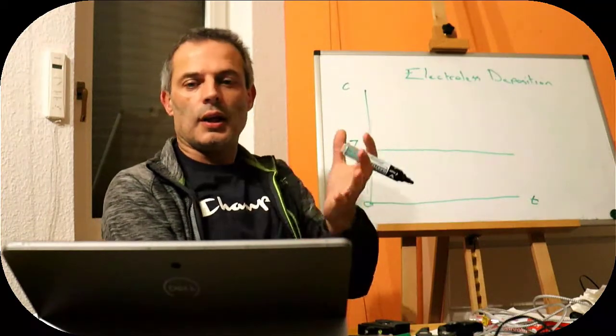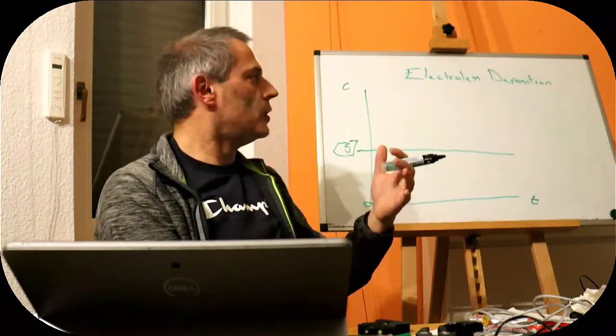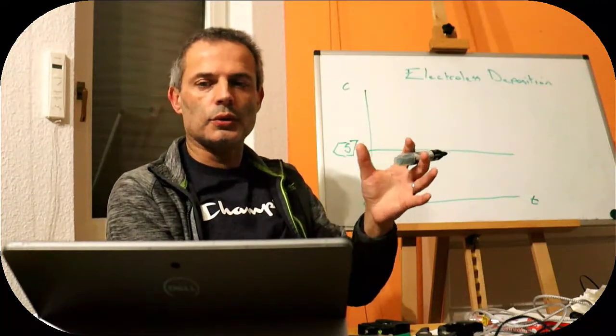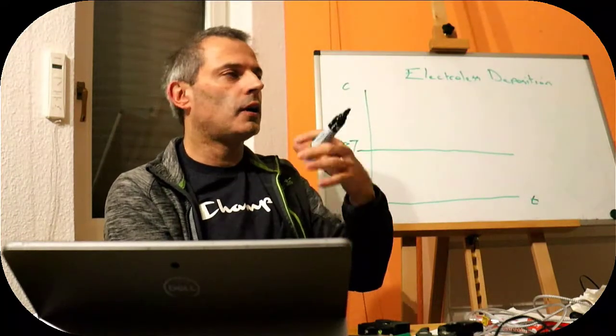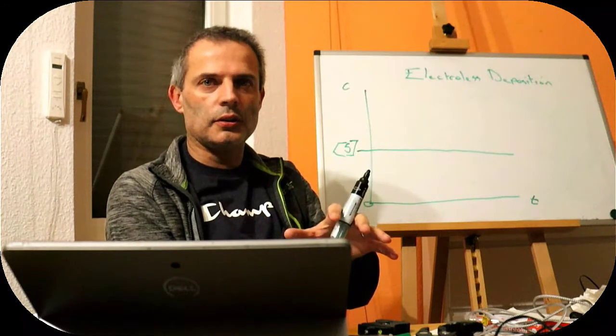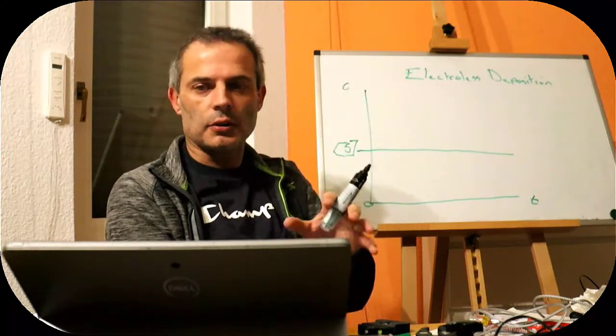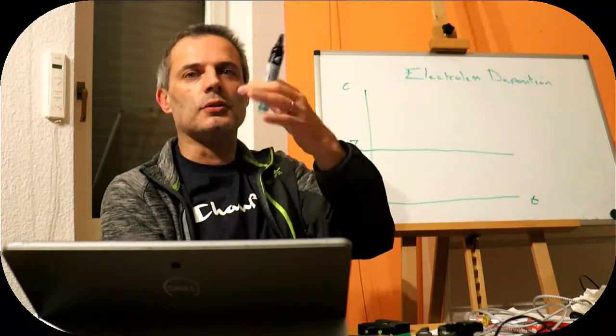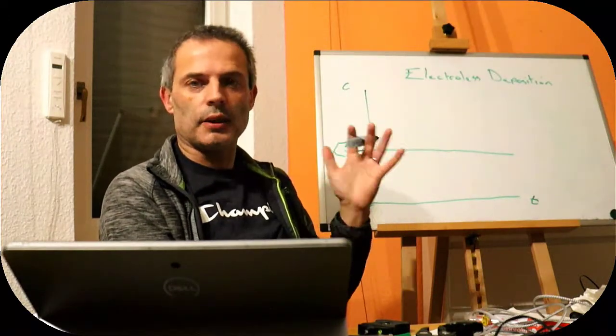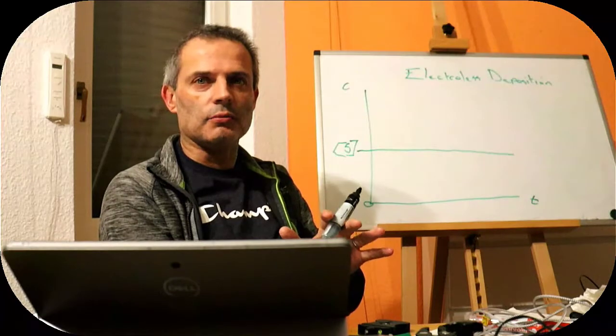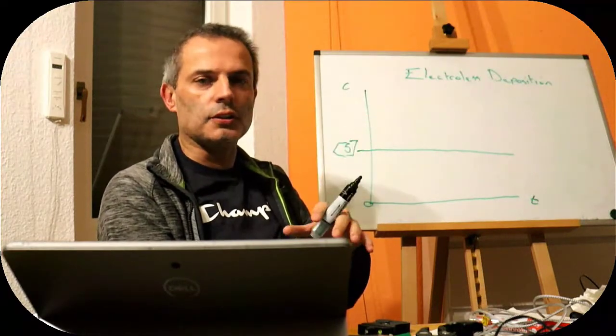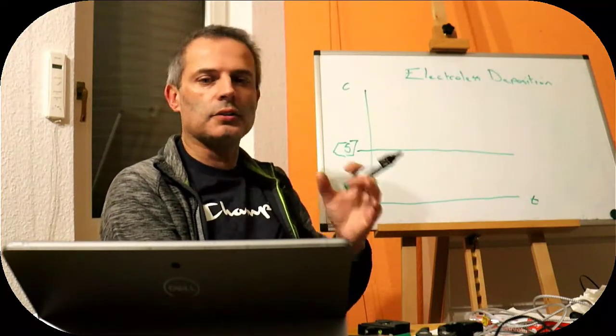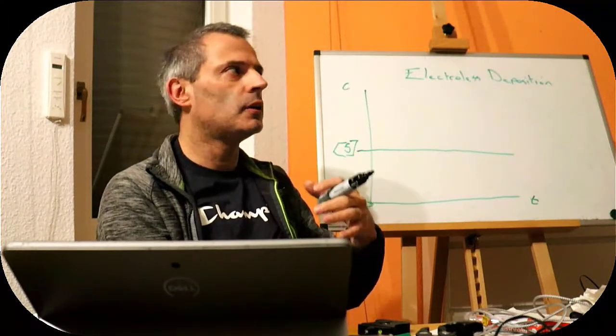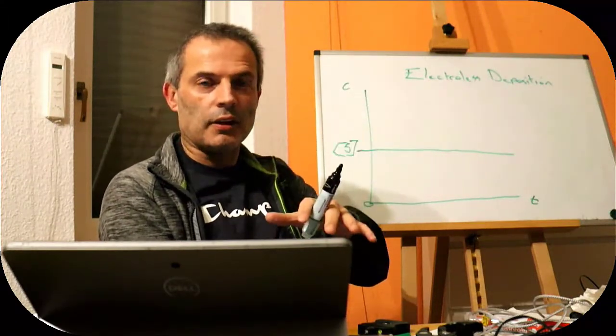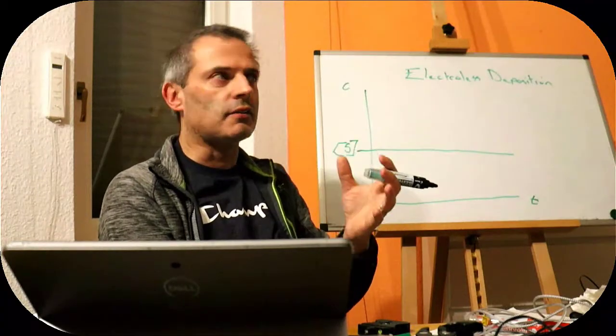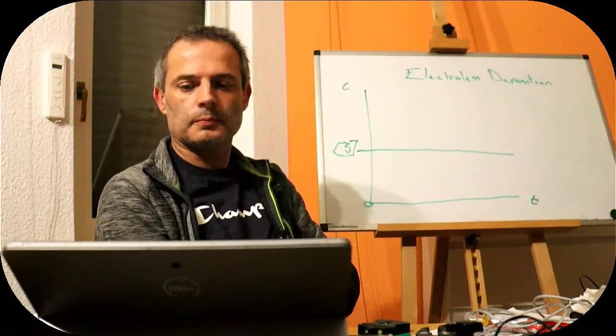And if you recall, in thermodynamics or in physical chemistry, we did the same thing. We cooled down some water and we passed 0 and nothing happened. It didn't turn into a solid until it had passed 0 considerably, and then it came back up in temperature to 0. Exactly the same thing happens here, and it's for exactly the same reason, that it costs surface energy to make a new particle, but it doesn't cost surface energy to grow a particle, because the surface area is replaced by less surface area per unit mass.